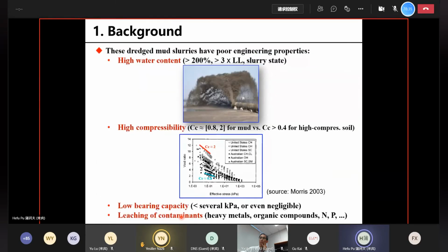And these dredged mud slurries exhibit poor engineering properties. For example, they have very high water content. Usually the water content exceeds 200%, and sometimes it's higher than 300, 400, or even 500%. So it's several times the liquid limit. So it's actually in a slurry state. So it's not really a soil, it's more like a mud slurry. It's more like liquid. And because of its high water content, it's usually in a loose state. So it usually has